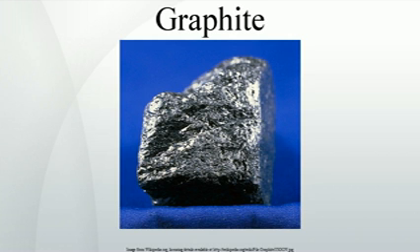This caused the failure of the Germans' World War II graphite-based nuclear reactors. Since they could not isolate the difficulty, they were forced to use far more expensive heavy water moderators. Graphite used for nuclear reactors is often referred to as nuclear graphite.